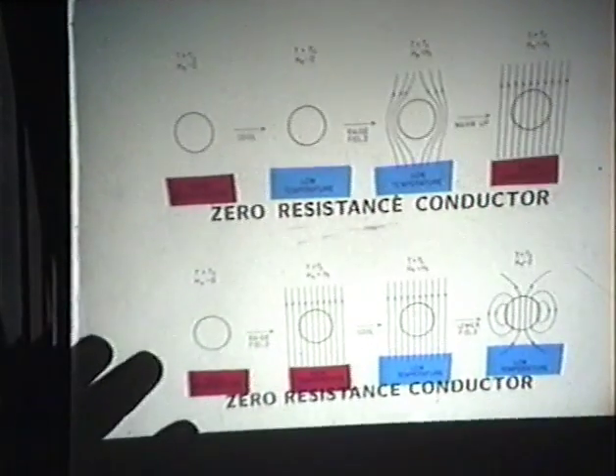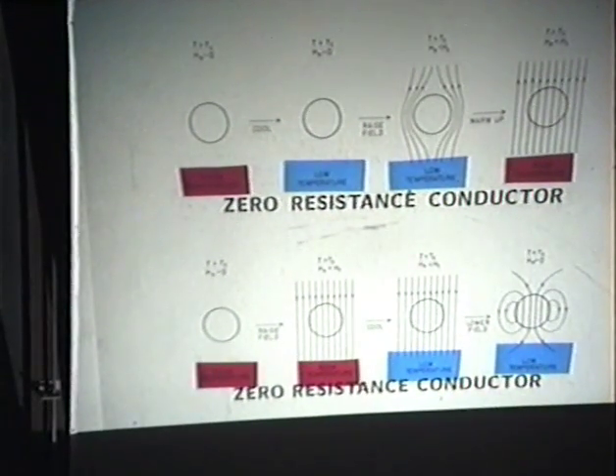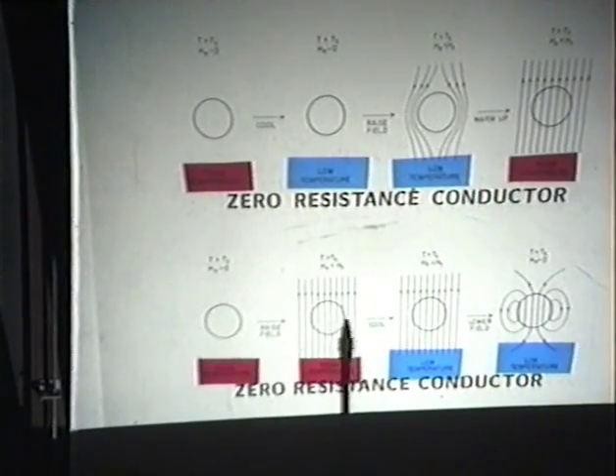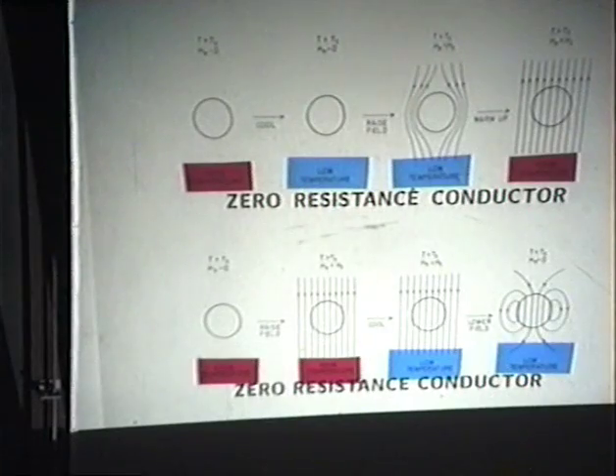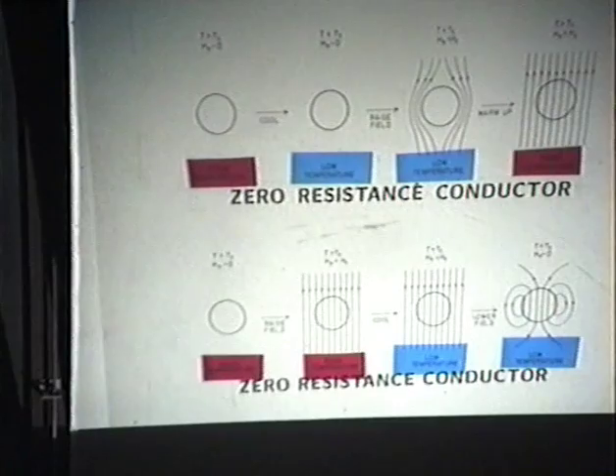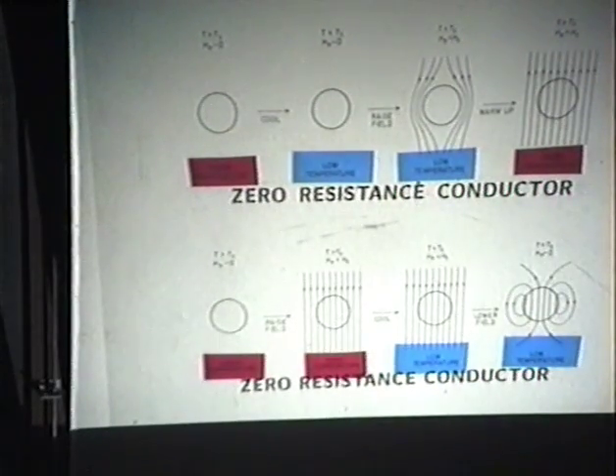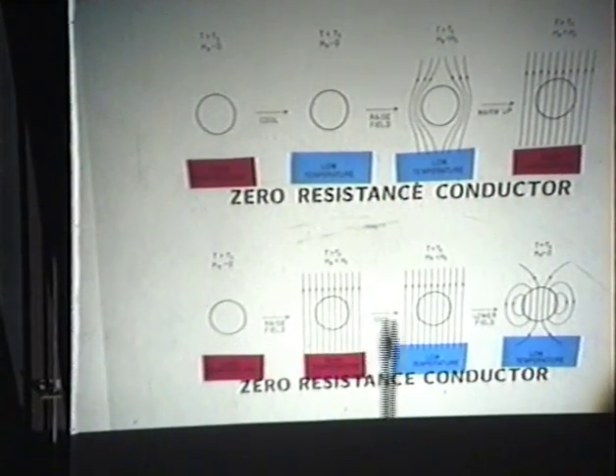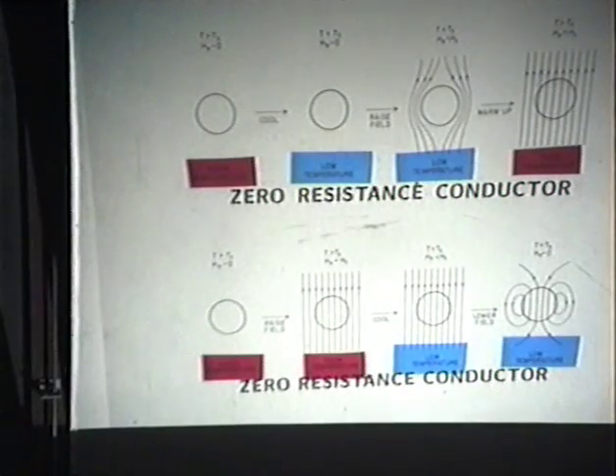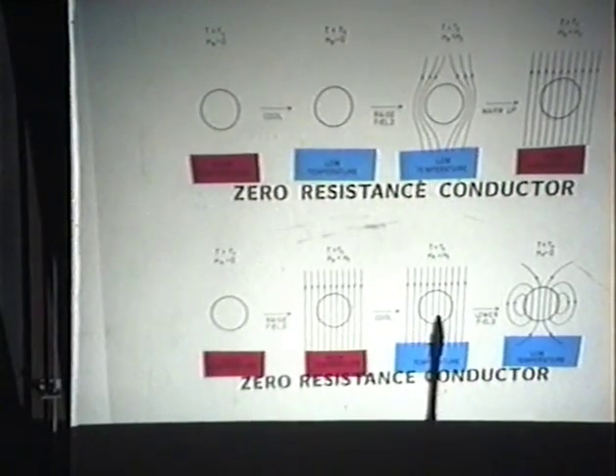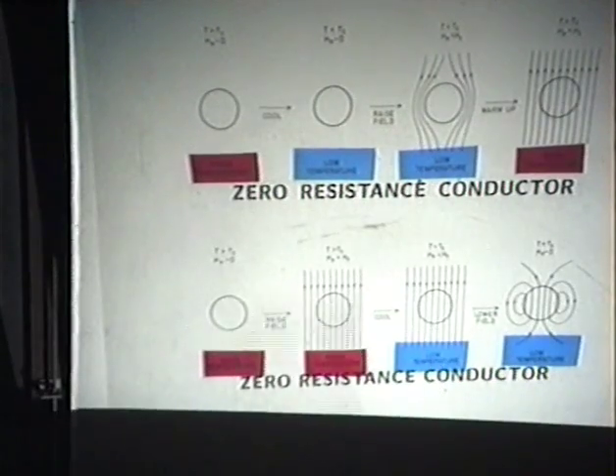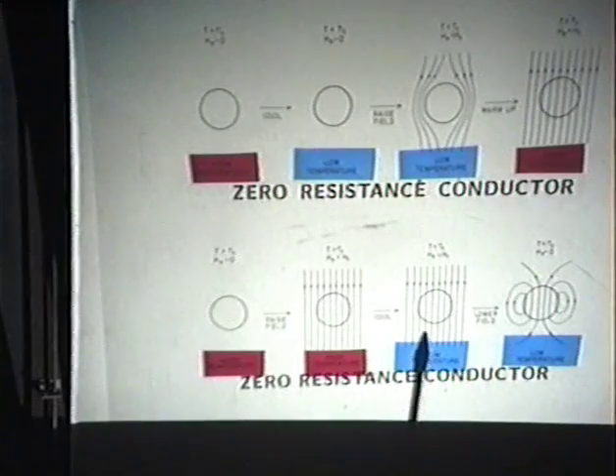Okay, let's do another experiment where this time you start your superconductor in its normal state at room temperature, and you put on an external magnetic field while it's in its normal state. Any eddy currents that you generate when you turn on the magnetic field will quickly dissipate because it's normal, and then you cool the superconductor down. Now when you cool it down it enters its superconducting state, but there's been no change in magnetic flux here. The magnetic field, I'm assuming, has just remained constant while you cooled the thing down.